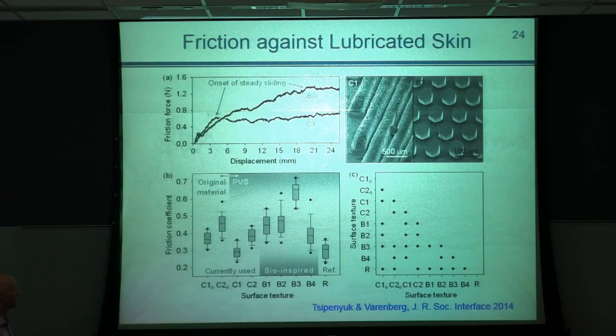C stands for commercial, B stands for biomimetic. So the commercial structure was able to generate a certain force, this is the curve, and this point represents the onset of steady sliding. While testing the biomimetic surface in the same conditions, this is the result that we obtained. It was able to generate about 2 times the friction of what we use in real life safety razors.